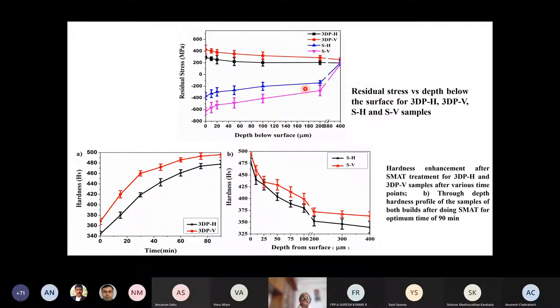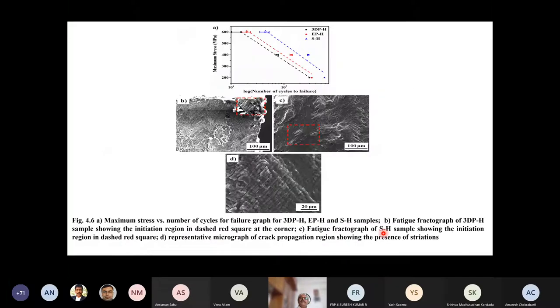For example, with surface mechanical attrition treatment, the residual stresses remain negative as we go below the surface up to about 200 microns, in contrast to positive residual stresses, which were detrimental in the as-deposited or as-manufactured condition. And there is an increase in hardness in this case, and with depth from the surface, it decreases. So basically, we tailor only a small region, but it has significant properties.